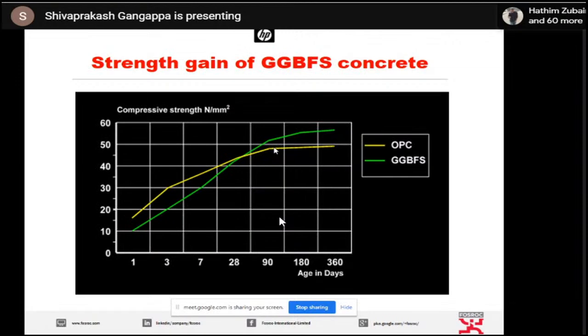The next replacement is you can go with the GGBFS. In case of GGBFS, what happens? Your break-even point is at 28 days. The advantage here is I can further squeeze down the water cement ratio. Thereby, I can take this green line to the yellow line in the initial days. So up to 28 days, it will be on par with the OPC. Then beyond 28 days, definitely OPC plus GGBFS concrete will be better.